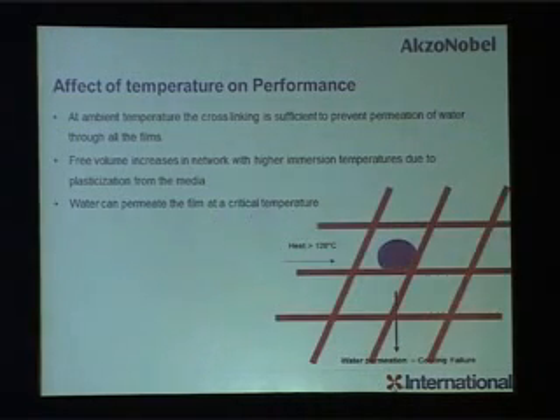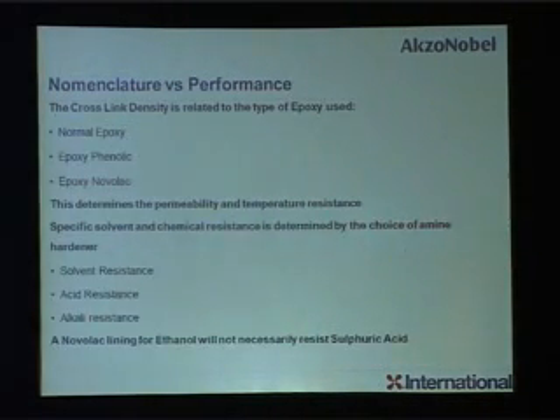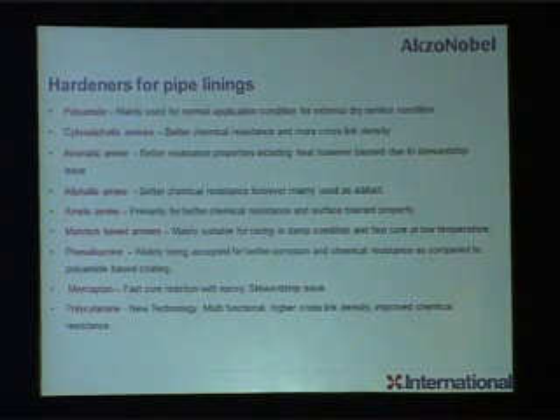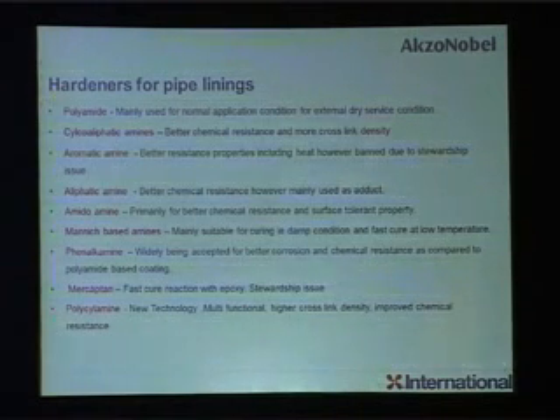I have another 2 slides. Now, as I said, all these properties of the coating, chemical resistance and everything, depend on the functionality of the epoxy resin. It is also a 2-pack, like epoxy getting cured with different types of amines. So as you play with epoxies like normal epoxy, epoxy phenolic, and epoxy novolacs, you can also work with a lot of curatives like polyamides, cycloaliphatic amines, aromatic amines, aliphatic amines, mercaptans, and recent developments like some polycycloamines. Now we have a lot of applications, like in gas pipeline coatings. They are looking for better flow and minimum chemical resistance. So people normally prefer amines or polyamides.